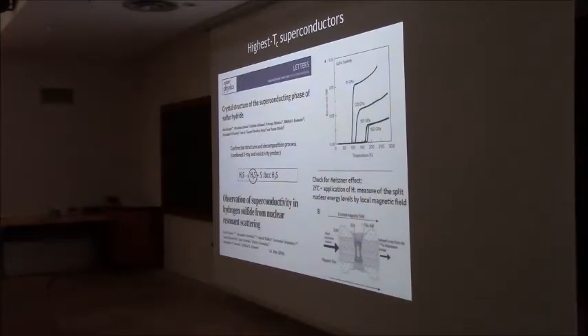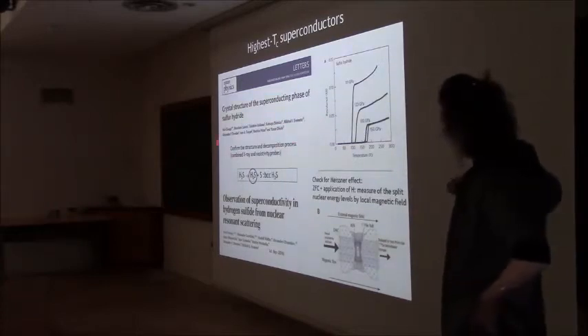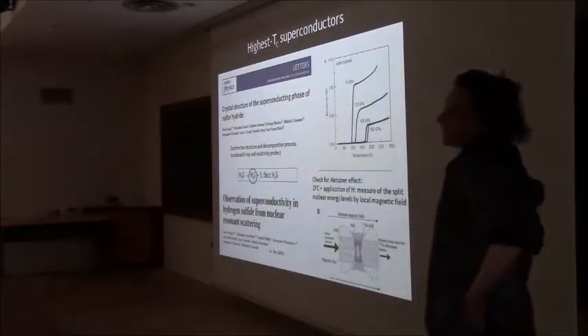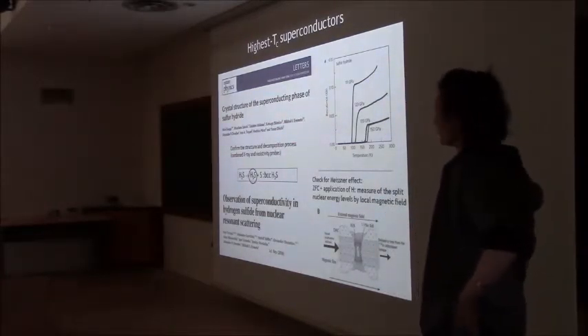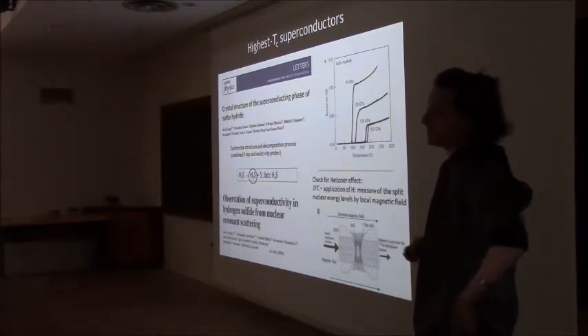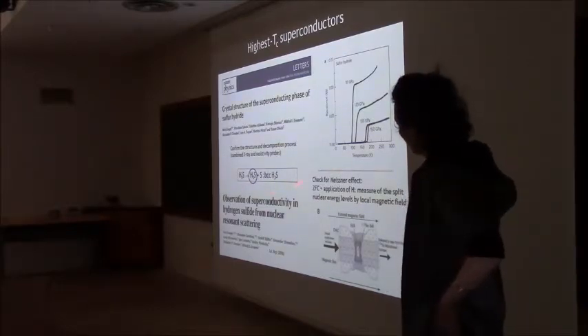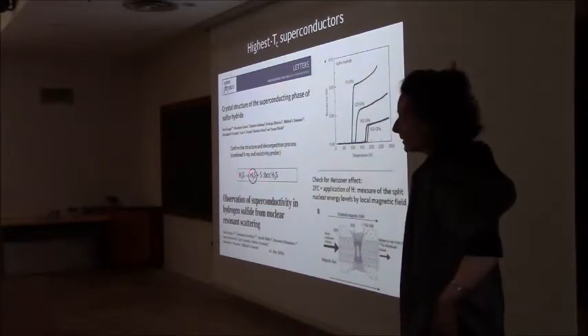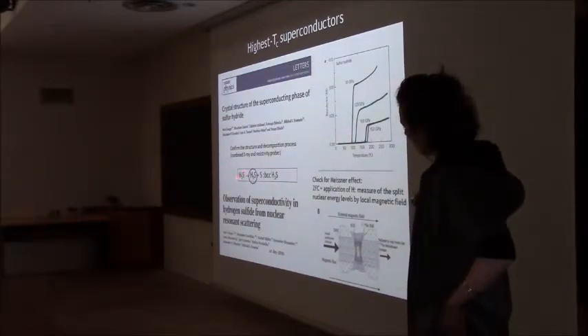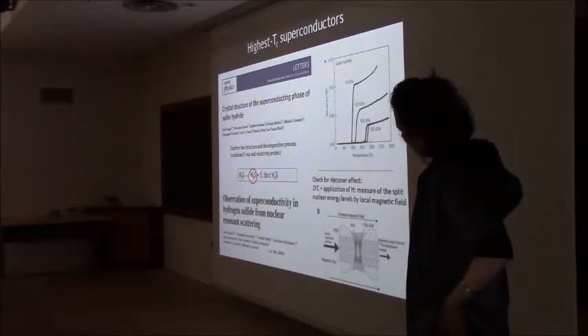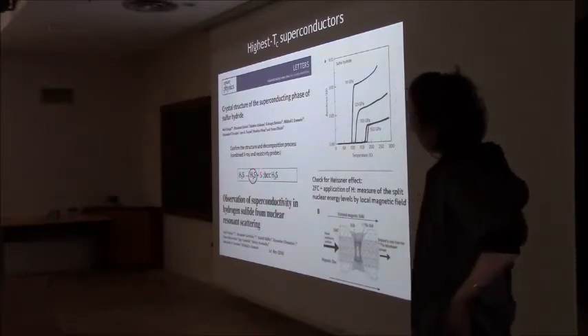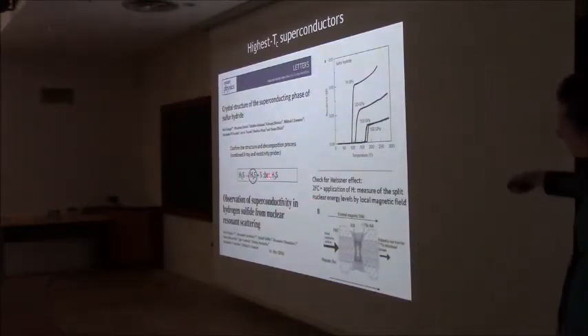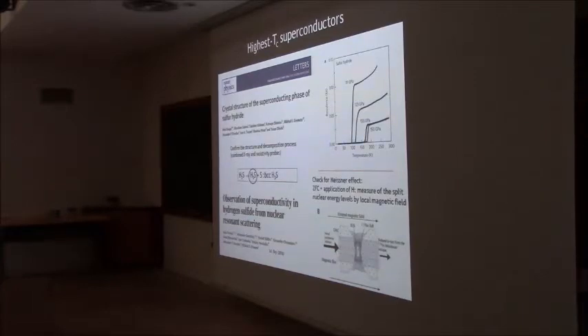So what are the updates? This nice paper, they combine X-ray measurement to check the structure and resistivity measurement. And so they confirmed the first idea, which was that this gas under high pressure, you finally get sulfur alone, hydrogen-free sulfur, which is expected to be a BCC lattice.